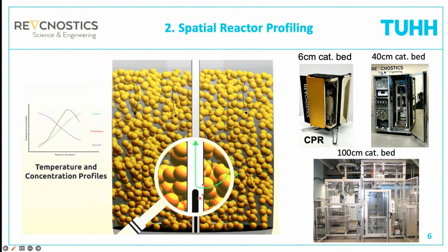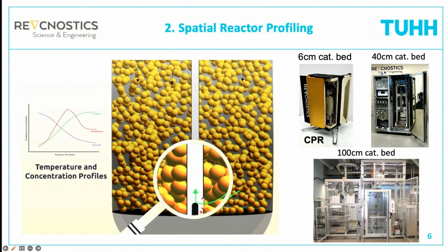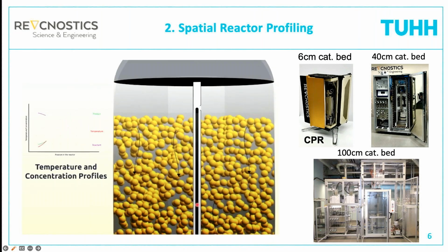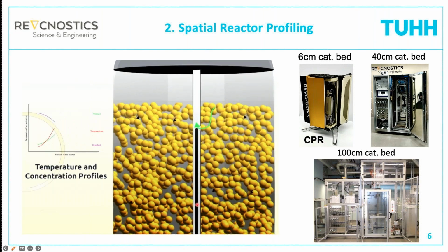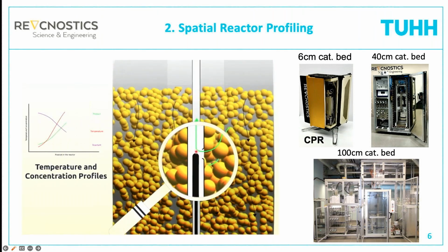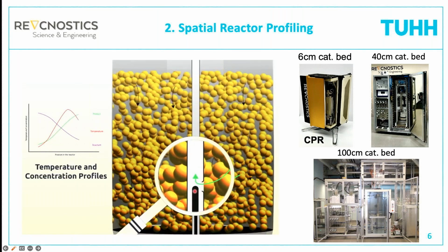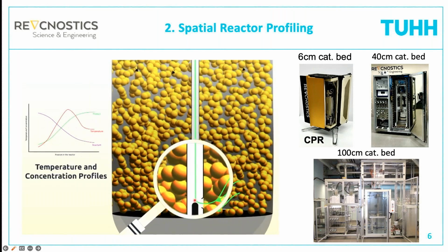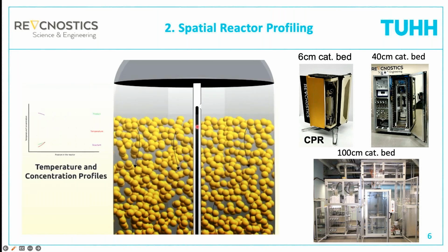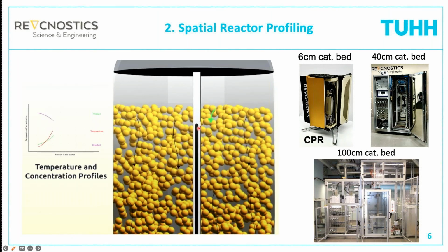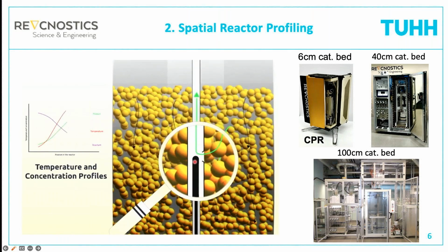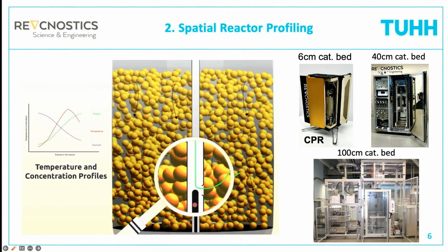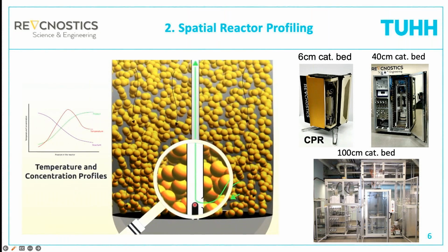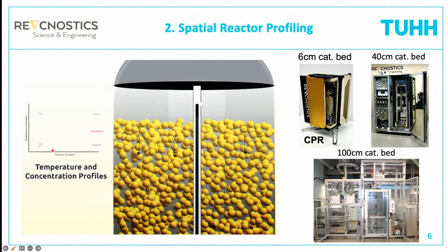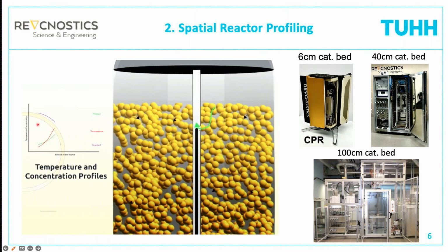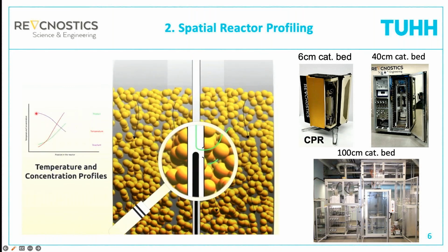So at the position where we have the orifice, we can determine the quantitative composition of the reaction mixture. And then inside the capillary, we have a temperature sensor, which can be a thermocouple or a pyrometer fiber, where we can also measure the local temperature. Now we move this capillary relative to the catalyst bed with a high resolution, and then we can measure concentration and temperature profiles, as you see here schematically in the left graph.